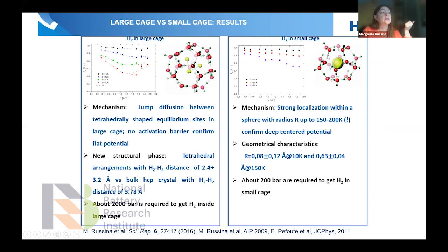And it turned out that in the small cage we have the confirmation that this hydrogen itself is localized within the center, within this very small sphere, whose radius is relatively small even at temperatures as high as 150 Kelvin, while in the large cage the hydrogen is moving between the 4 tetrahedrally shaped positions, and this is how the landscape is. This is exactly due to the potential minima, to the potential landscape.